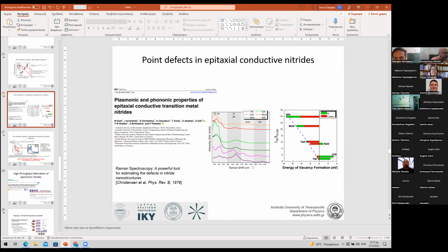So in the case of tungsten nitride, because in the calculations they were dealing with a perfect crystal, it was predicted that it would be a very good material, but then the experiments have shown that there are a lot of defects, which were afterwards explained again from new calculations. But from the beginning, for the case of tungsten nitride, we did have some problems. I'm not an expert in designing, frankly, so I don't feel that I can give you a firm answer on that. What I've done was just to calculate the band structure, and from that have a pre-screening of material, nothing more than that.